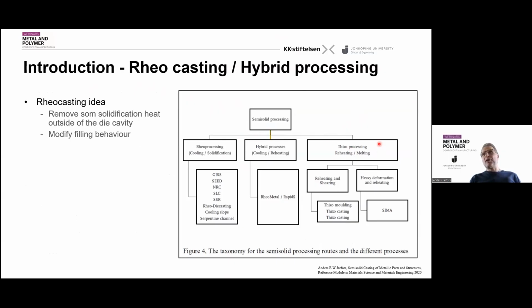We have thixoprocessing. That means that you reheat and you remelt something. And this is typical thixomolding, which is used in magnesium materials. And then we have rheoprocessing on the other side, which is a process where you cool down and you allow it to solidify. And a lot of the processes today, like the GISS and the SEED process, a new Rheocasting process, are found here.